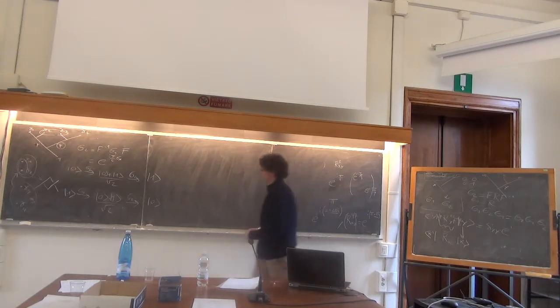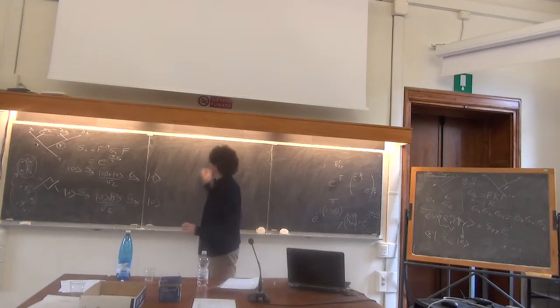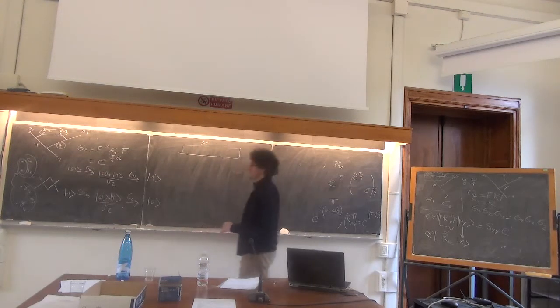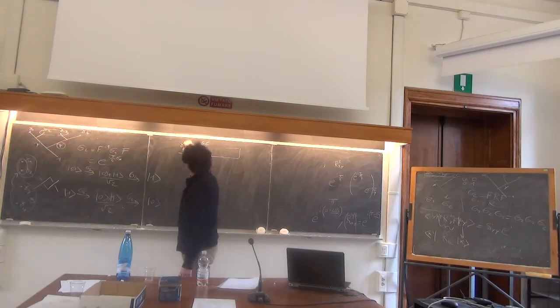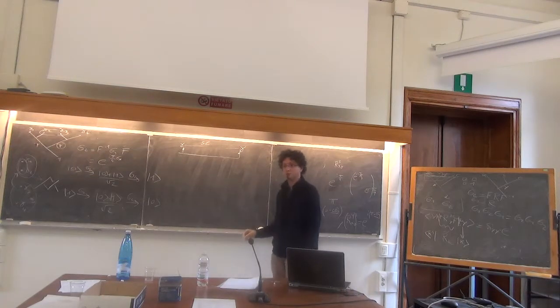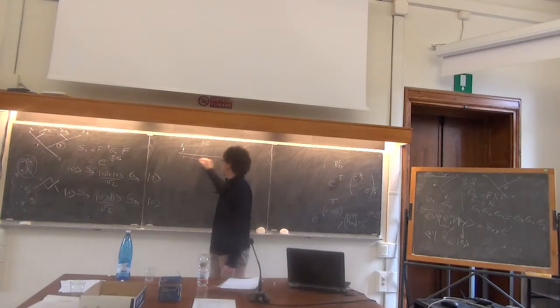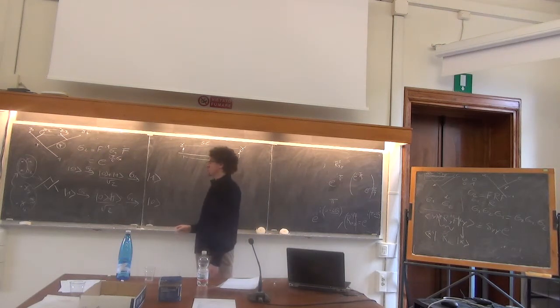But the trick is that essentially you want to have a system which is usually some superconducting system, and tomorrow we will see it better, in which you obtain Majorana modes that are far enough not to be interacting, so that this distance must somehow be great with respect to the coherence distance of this superconductor.